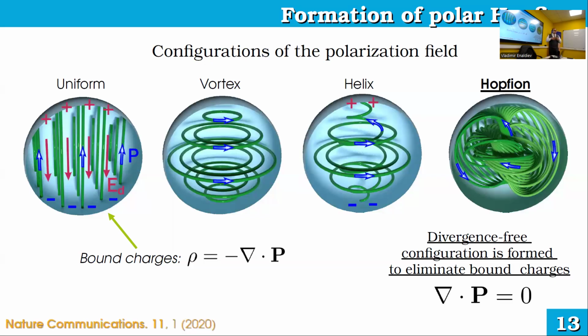Okay, so to get rid of these bound charges, we need to get to a divergenceless state. The obvious configuration is just a vortex, and actually it's a stable configuration because you see the lines of polarization in a vortex are tangential to the surface of the nanoparticle. And actually it's a stable state near the temperature phase transition. But there is one problem. The problem is here you have a singularity in the very middle, in the core of the vortex, yes? And a ferroelectric system tries to be as uniform as possible. So the polarization vector should be very uniform. Okay, we can get rid of this too.